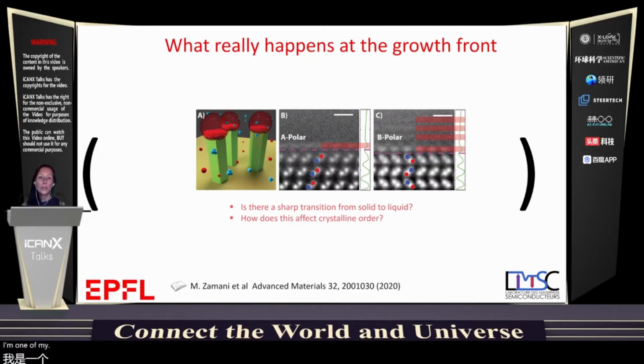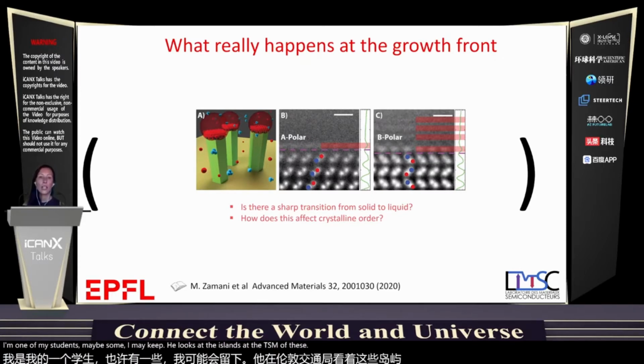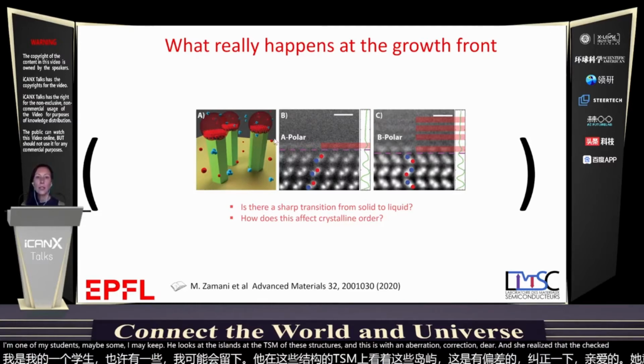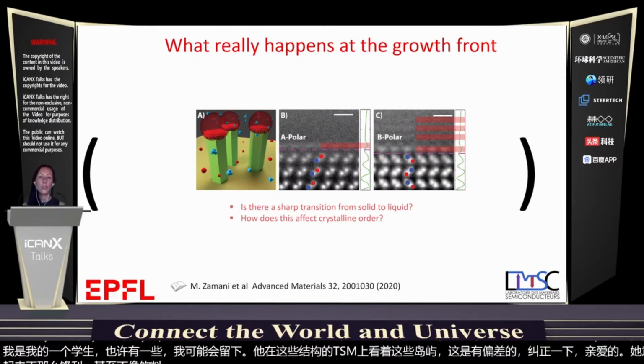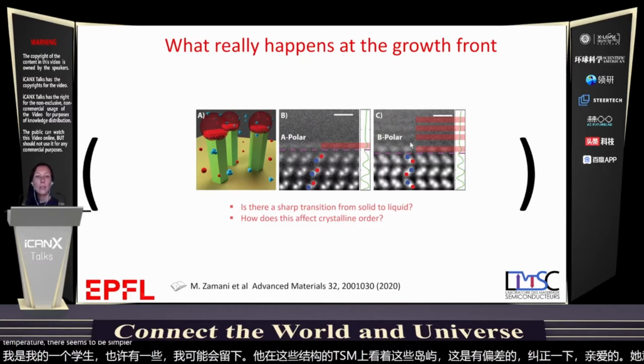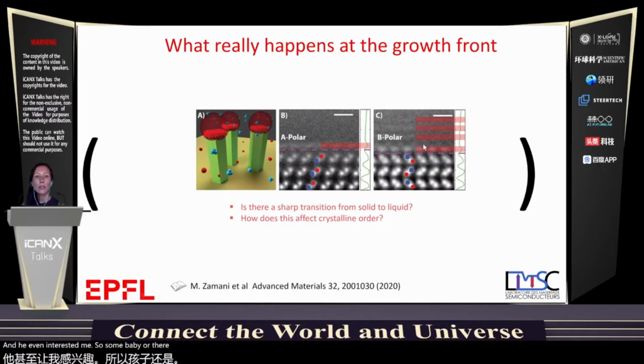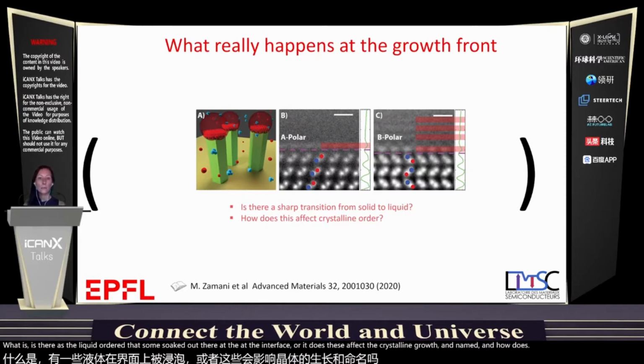One of my students, Madi Zamani, looked at the TEM of these structures, and this is with an aberration-corrected TEM, and he realized that in fact, the liquid-solid interface doesn't seem to be so sharp. Even at room temperature, there seems to be some blur, and he even intuitively saw some maybe order that goes further away. So the question is, is there a sharp transition from solid to liquid, or is the liquid ordered close to the solid at the interface, or does this affect the crystalline growth, and how does it do it?